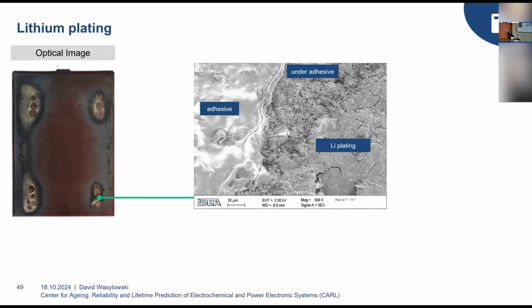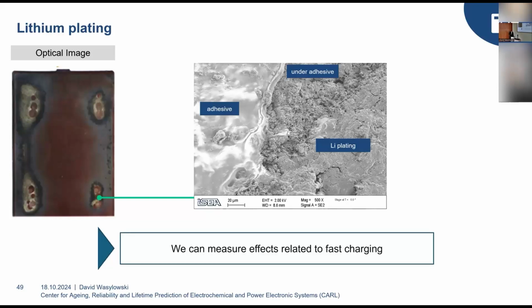But if we now strip away part of the adhesive, we can actually see that under this adhesive is perfectly pristine graphite, which looks like it has never been even cycled before, further confirming our hypothesis that this adhesive is actually blocking the lithium ion pathway and only allowing lithium charging to happen at this perimeter. So in conclusion, using ultrasound, we can measure effects which are related to fast charging and these local inhomogeneities.